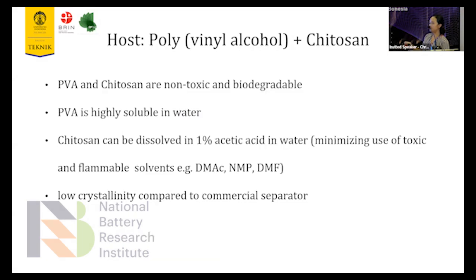And for this, we use the polymer host, polyvinyl alcohol, and chitosan, because chitosan is abundant and it is a waste. So we can actually process the waste into something that is much more useful. So the PVA and chitosan both are non-toxic and biodegradable. It is highly soluble in water. It can be dissolved easily in water or in just 1% of acetic acid.